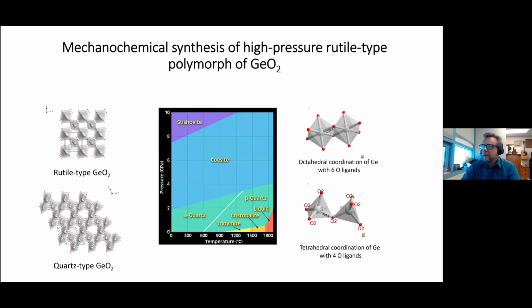So if you look at the germanium oxide phase diagram, it is very similar to silicon dioxide. We have the same types of phases, at least in the low pressure regime. So we have a quartz type phase that has 4-coordinated germanium. We have a 6-coordinated phase, which is similar to stishovite. It's the rutile type germanium oxide. We wanted to see if we could start with quartz and, by grinding in the high energy mill, transform it to rutile.